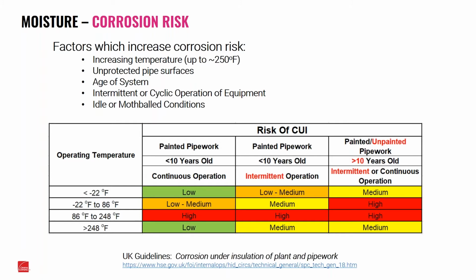So even as we move over to the next section where we look at intermittent operation, we are increasing our risk a little bit more. However, we're going basically from low to medium in most cases. But again, we still have that temperature range from 86 to 248 degrees. That's really the critical factor here.